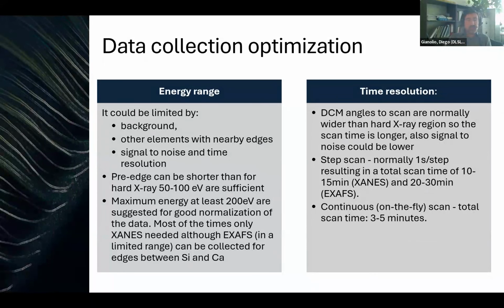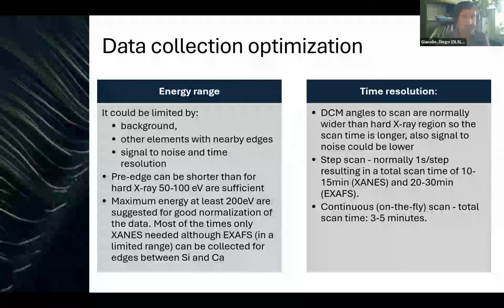So there are different ways to collect the data. As for hard X-rays, the most common in the tender range is still the step scan, where normally 1 second per step results in a total scan time of 10 to 15 minutes if you collect a short XAFS, or 20 to 30 minutes if you measure a full XAFS. It is also possible to do a continuous on-the-fly scan, with a total scan time that could range between 3 and 5 minutes. But here again, it is likely that you need multiple repetitions to improve the signal to noise.